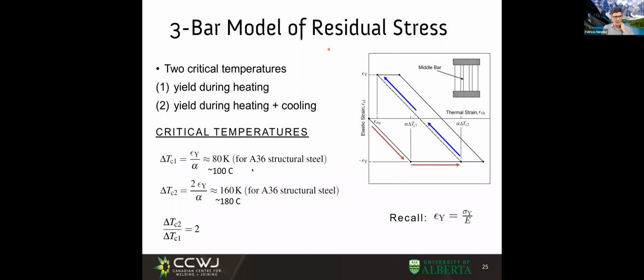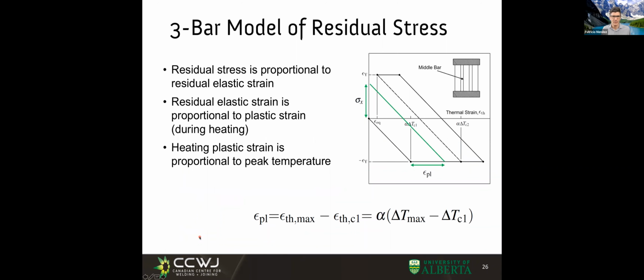So the ratio between these temperatures, the yield temperature in cooling and the yield temperature in heating, is a factor of 2, and we're going to see that it appears. So we can calculate the amount of plastic strain, how much it was deformed plastically, as how much it was deformed by expansion in total, and we subtract the limit at which it was elastic. And because it all depended on temperatures, this would be the maximum temperature minus this yield temperature. And this alpha is the coefficient of thermal expansion.